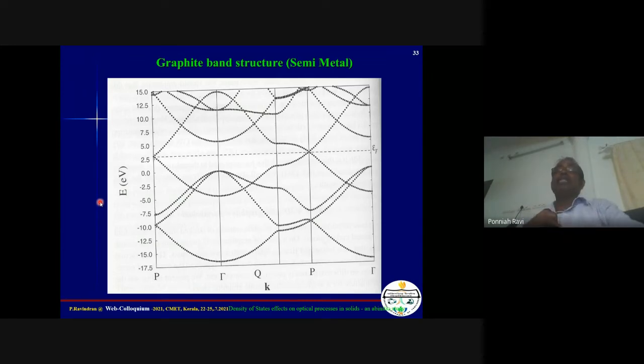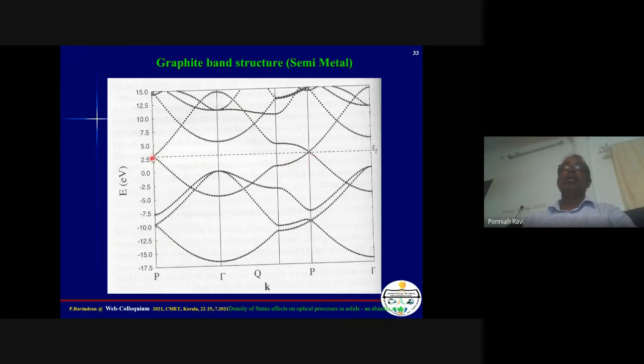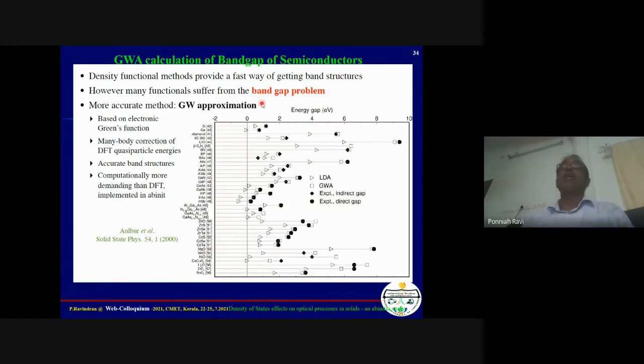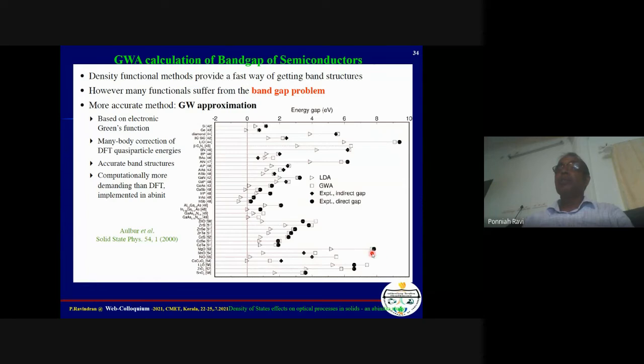Sometimes you hear about semi-metals — graphene is a good example. In a semiconductor or insulator there is a gap, but in a semi-metal the band gap is zero: completely filled valence band and completely empty conduction band meet with no gap. The calculated band gaps of various materials using GW approximation compared with experiment show: the triangles are LDA (underestimated), squares are from GW (quantitatively accurate). The computation involved is very large, but we can predict band gaps accurately.